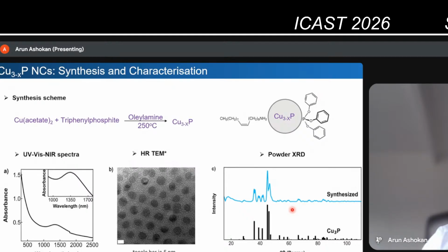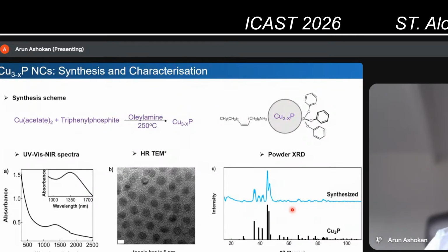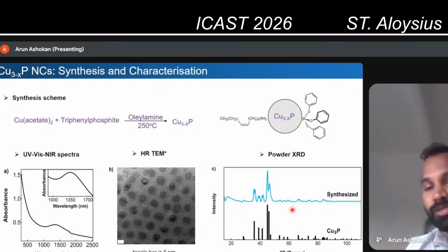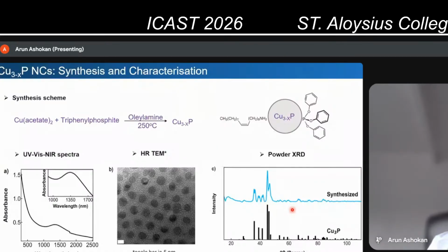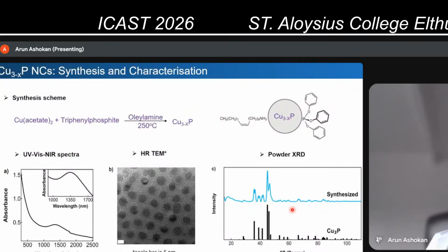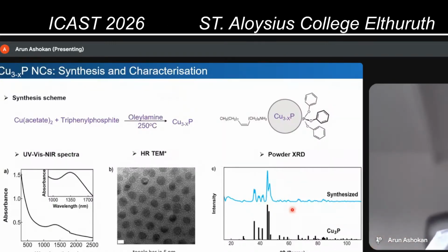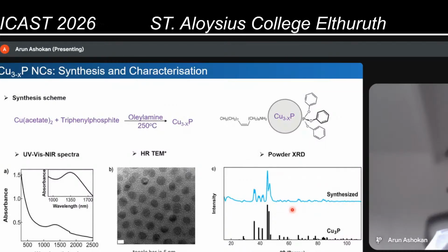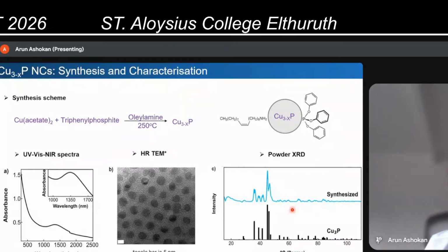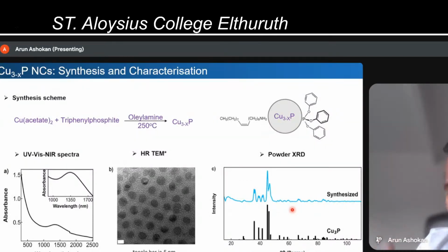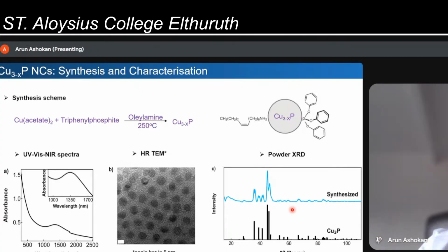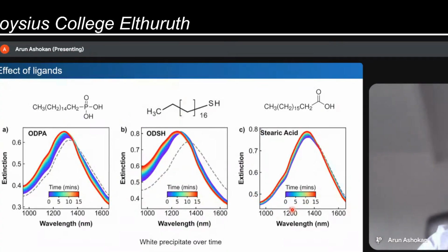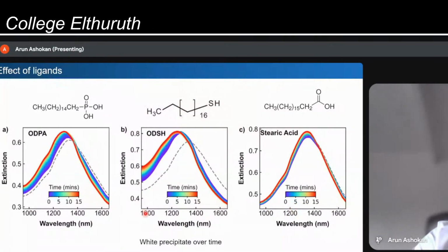So we need to tune the charge density, or basically we need to tune the charges in the copper phosphide nanocrystals. There are a couple of ways. I said the ligands bind to the surface, so we can also use the ligands to modulate the electron density and thereby the plasmon. So what we tried first was adding different ligands to these nanocrystals.